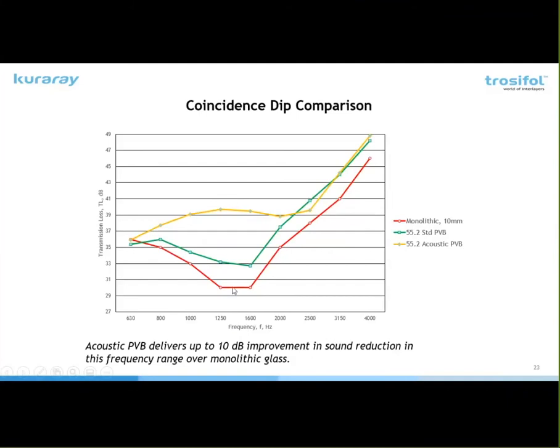So when we blow this up, in the area from around 1,000 to 2,000 hertz, there's quite a difference in acoustic performance. So while we were talking 3-point improvement versus a standard PVB and 5-point versus an acoustic PVB, that's a weighted average. If you go to this particular frequency range, you're talking about 10 points from monolithic glass to an acoustic laminated glass. And 10 points, 10 dB, is basically you're cutting half the sound down by going to the laminated glass with the acoustic PVB. So it's very significant in this range. And really the range of hearing that we're most sensitive to is in the 1,000 to about 5,000. So it's cutting out a big chunk of sound in the range that we're quite sensitive to.